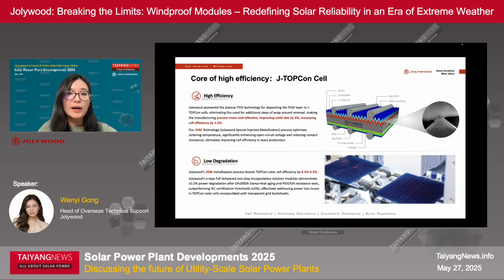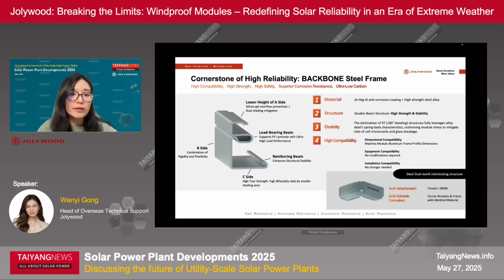So the cornerstone of the high reliability is the backbone steel frame. Here is a cross-section of our backbone steel frame. We can see it's very different from the conventional aluminum frame. The A side here has a much lower height. It's 1 millimeter lower, so it can prevent the silicon gel overflow and also mitigate the dust shading